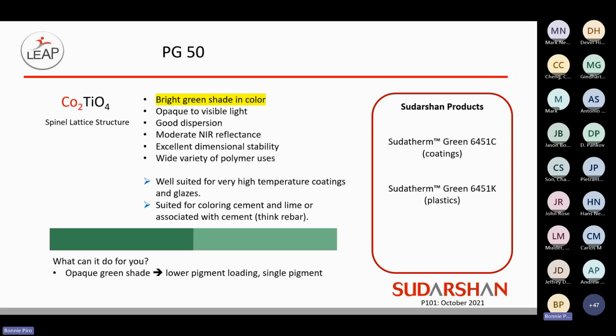And the cobalt green is Pigment Green 50. So like its counterpart, it's well suited for high temperature coatings and glazes, for coloring cement or applications associated with cement. So here, think rebar going into cement in there. This is a good option for that one. And like the blue, it being an opaque green shade with one pigment, you have the potential of a lower pigment loading with a single pigment.